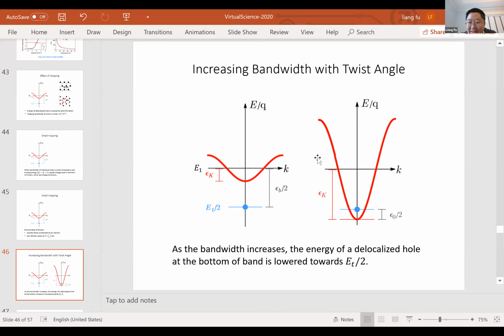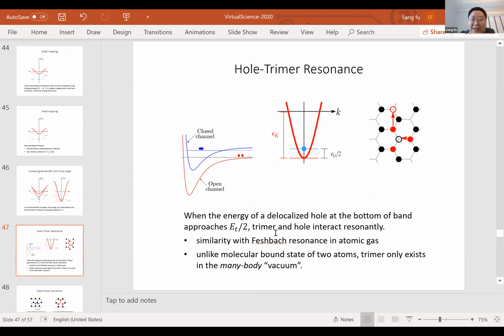But I think the more interesting case is to consider increasing the hopping amplitude, and this can be achieved again by the twist angle. As we move away from 0 degree, the moiré unit cell decreases, the hopping gets stronger, the bandwidth of holes increases, right? So as the bandwidth increases, the energy of this delocalized hole at the bottom of the band gets lower and lower towards the energy cost of a trimer. And this is the regime that I want to focus on. So in this regime, the resonance happens. When the energy of a delocalized hole at the bottom of the band approaches the energy of the trimer, trimer and hole interact resonantly with each other.